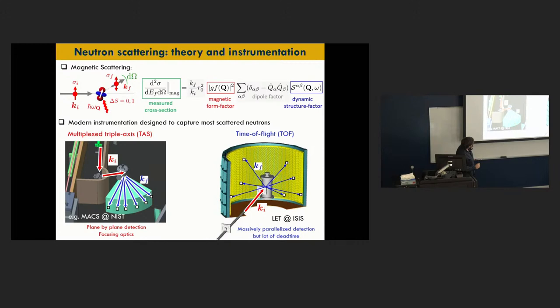So it's coming at a certain frequency, which is 60 hertz, impinges on the sample, and then the sample will scatter the neutrons in a large area detector, which is of the order of 5 meter by 5 meter, you know, millions of pixels. So in some way, it's a parallelized detection system. And because we do time of flight, we can simply measure as a function of time to reconstruct the energy of the neutrons that are impinging on the detector. So this is a very efficient way to do neutron scattering. Okay. So time of flight neutron scattering.